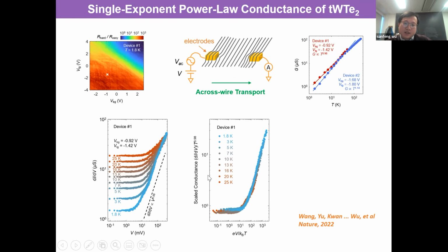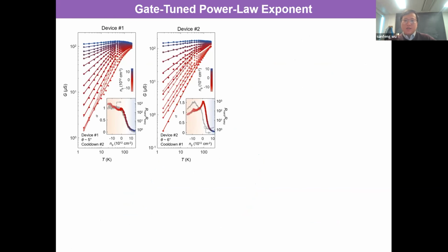They collapse in a scaled plot where you only involve alpha, T to the 0.98 in this case. All data collapse onto the same line. So this really says that the conductance as a function of temperature or bias is dominated by a single exponent alpha, which is the same, right? So that's why they can collapse. So the single alpha exponent is really a key in demonstrating the Luttinger liquid characteristics.